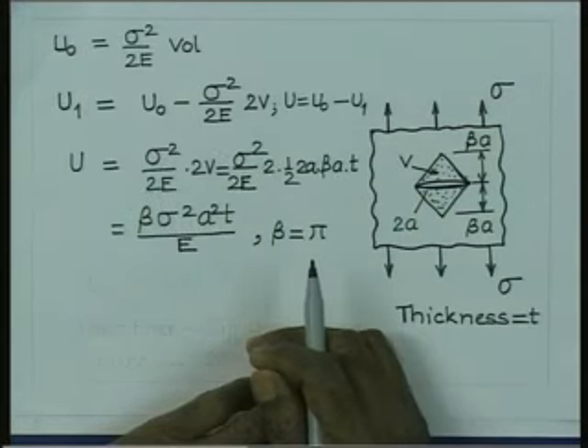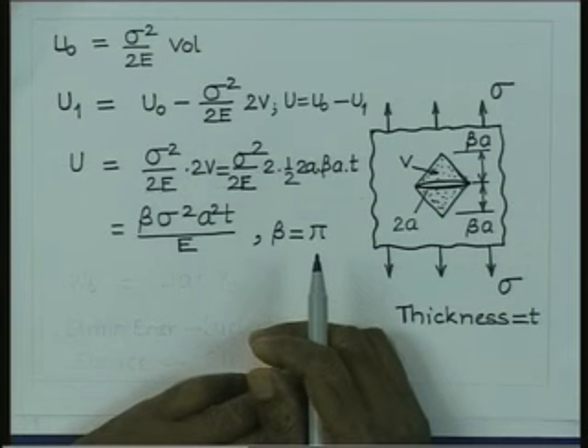So, I would like to repeat this point again, that when we try to pull the material to break the material bonds, we give some input energy, and as soon as the material bonds are broken, the energy that we have given as input gets converted into the surface energy, and therefore, the energy gets stored at the surfaces. And if we consider that the surface energy of the material is a constant, then if we have a crack